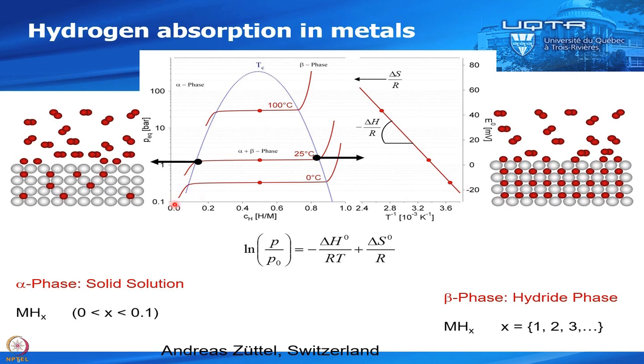So that's the thermodynamics. So you have your metal, and this is the pressure of hydrogen. This is the capacity of hydrogen, so it's the number of hydrogen atoms over the number of metallic atoms. And as you start, you increase the pressure, hydrogen will enter in solid solution in your metal, up until you reach that point. At that point, you start to nucleate the metal hydride phase. Okay, so usually it has a different crystal structure.